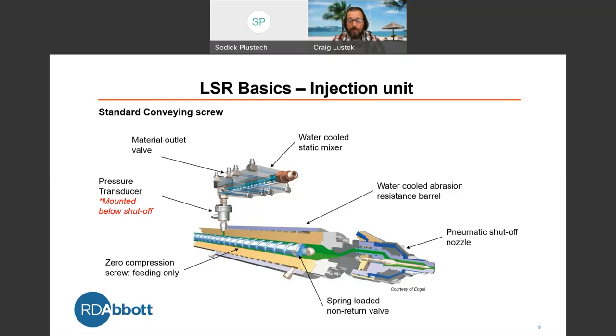Spring-loaded non-return valve. This allows us to shut off, and because of the material being viscous, when we inject, we won't get back pressure pushing back up through the system. We want to make sure we're keeping that shot in front of the non-return valve. The water-cooled abrasion resistant barrel, again, we're creating friction and heat in there. We want to keep things cooled down, ending with our pneumatic shutoff nozzle to put material into the mold.